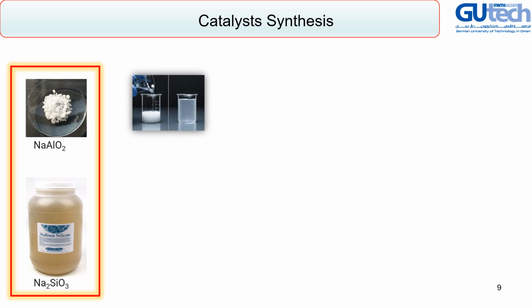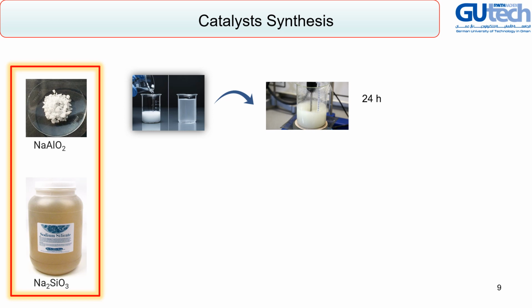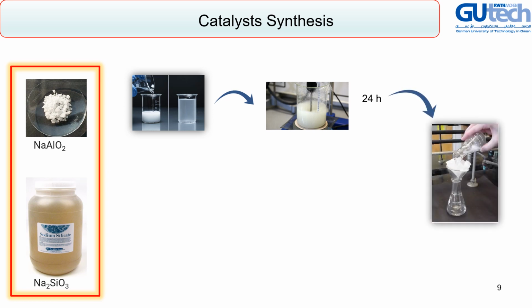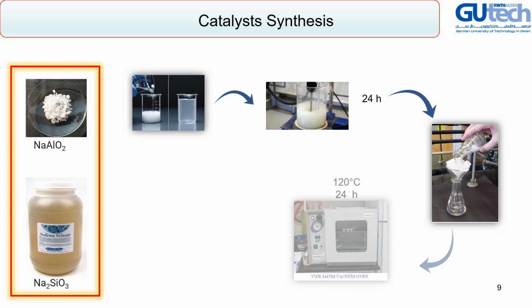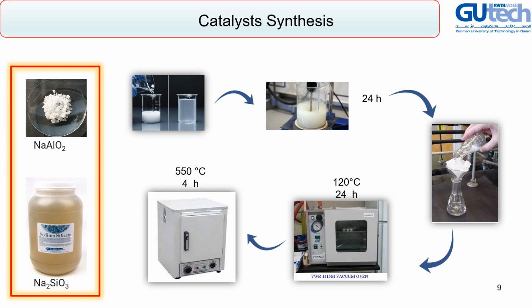Catalyst synthesis starts from mixing two main materials, which are NaAlO2 and Na2SiO3, sodium aluminate and sodium silicate. We dissolve them in deionized water, and then mix these two together to obtain a gel type solution. It can then remain at room temperature for 24 hours. Then filter the solution and leave it in the oven at 120 degrees Celsius for 24 hours to dry out the catalyst, and finally calcine in an oven at 550 degrees Celsius for 4 hours.